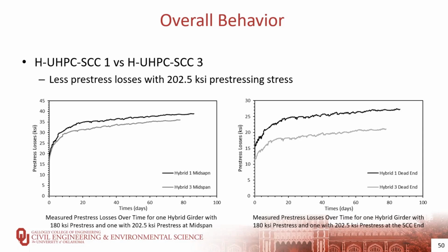In this comparison, hybrid 1 was prestressed to 180 KSI, whereas hybrid 3, or the UHPC SCC3, was prestressed to 202.5 KSI. The figure on the left presents the measured prestress losses over time for both girders. Unexpectedly, the midspan losses over time for hybrid 3, which had a higher prestressing stress, were less than hybrid 1, even though more prestressing stress was applied.